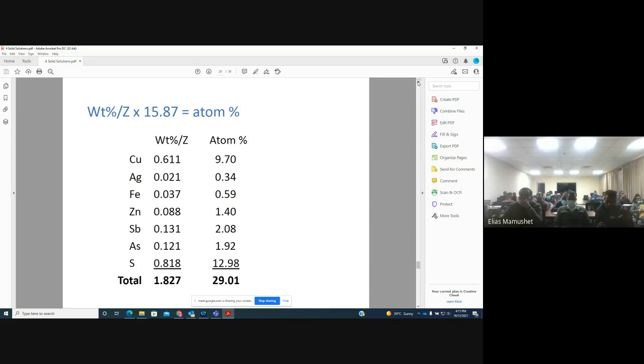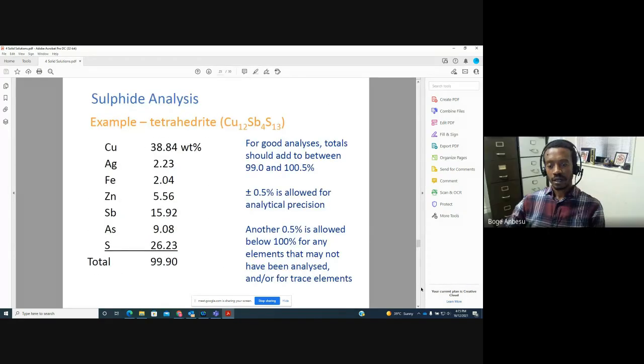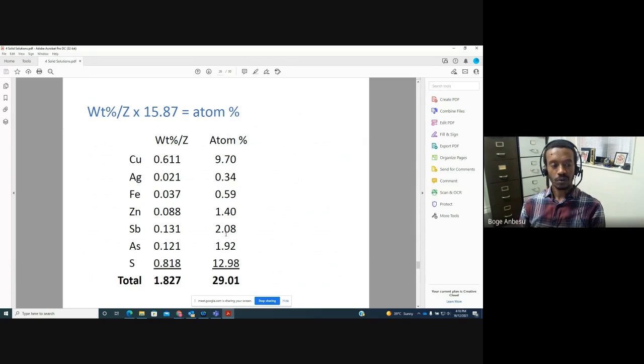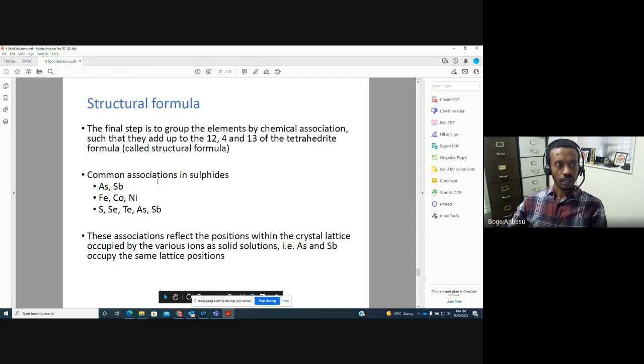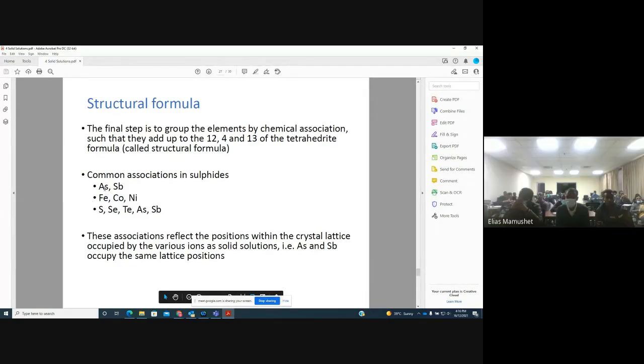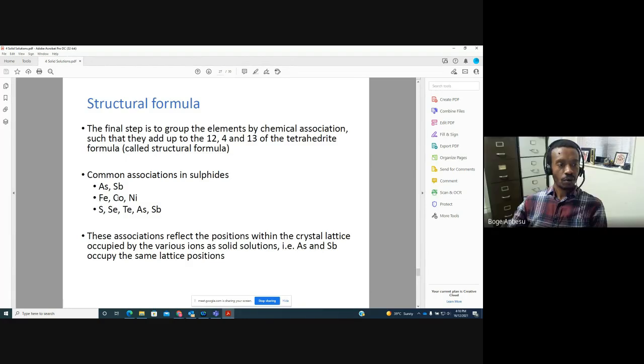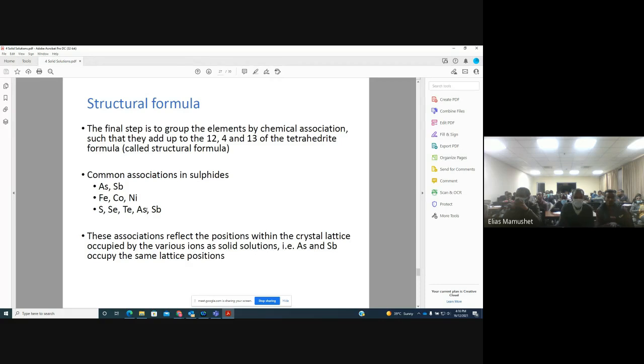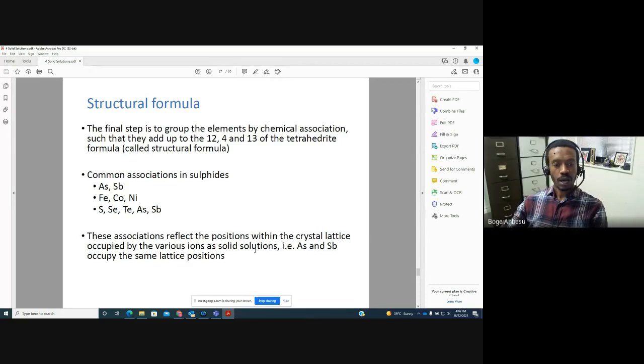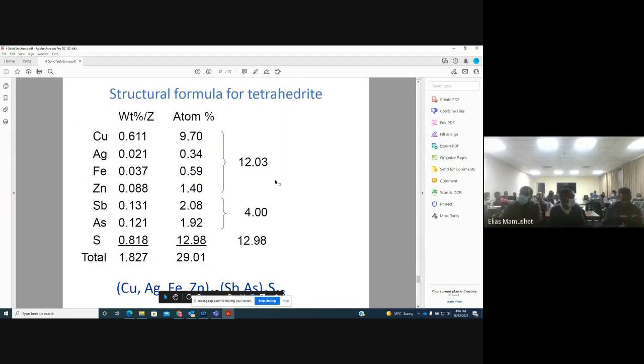The other one is I have 4 antimony here, but I have only 2.08 antimony here. That's because the arsenic was replacing some of the antimony. I expected 13 sulfur, I have 13 sulfur. So overall, the arsenic replaced the antimony, the iron, cobalt, and nickel replaced some of the copper, and some of the sulfur can be replaced by tellurium, selenium, arsenic, and antimony. But in my example, this is actually not shown. So I don't have tellurium, I don't have extra arsenic. Therefore, when you add everything up, you should get something like this.